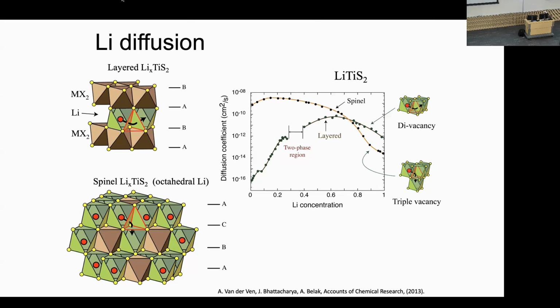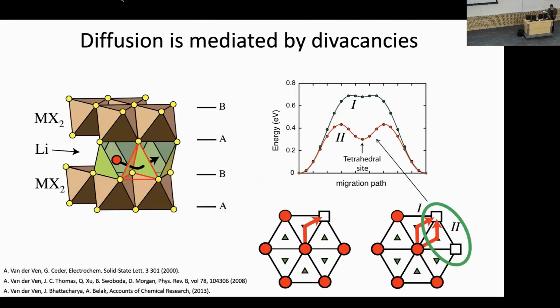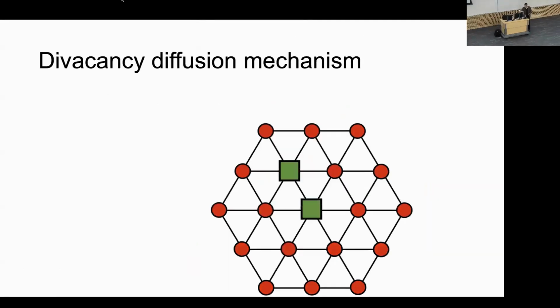A lot of that has to do with dimensional changes of the crystal, so lattice parameter variations as you change the lithium composition, but also at higher compositions, because in the layered materials, diffusion is mediated by divacancies, whereas in this spinel, it's mediated by single vacancies, and those kind of start running out at high composition. I did say this was my last slide, but I think the next one is just to illustrate, this is a very inefficient mechanism of diffusion with these divacancies. And so that's why the diffusion coefficients have such a strong composition dependence at high composition. So I'll end there. Thank you very much for your attention.